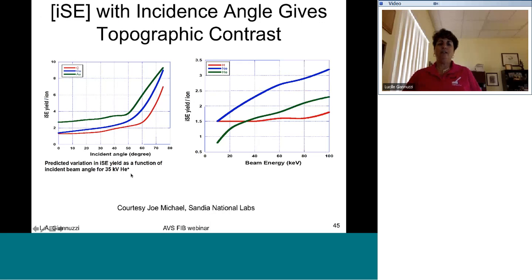Okay, ion-induced secondary electron signal gives you topography very similar to an SEM type of topographic contrast. That is, as the incident angle increases, the secondary electron yield increases. You also see that the yield will vary very much with different ions. And you see you have this crossover here at the low energy with helium and hydrogen and neon.